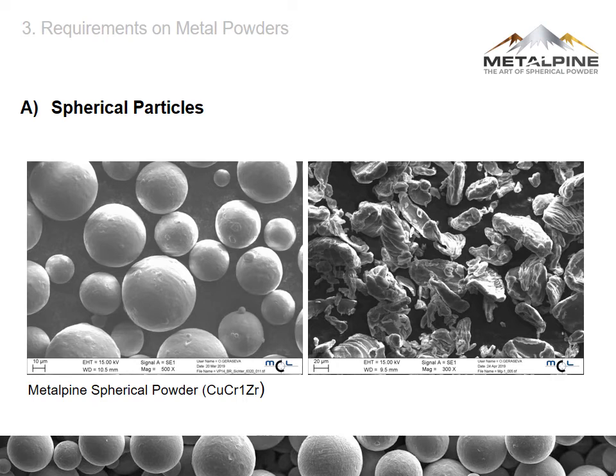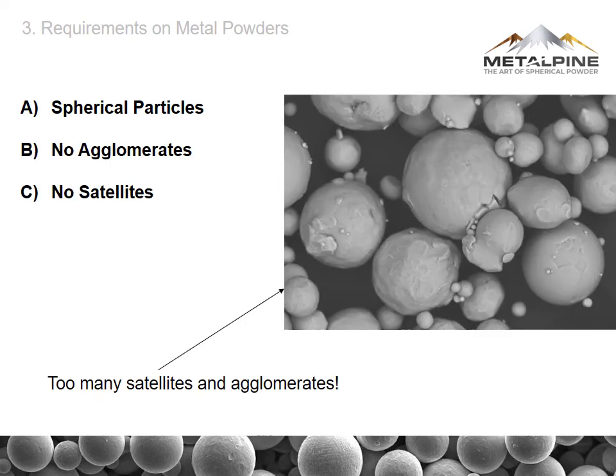So, of course, spherical particles are flowing better and have got a lower surface area than the particles which result from a grinding process here on the right. But you would also want to have only very few agglomerates, as any agglomerate may increase the probability of defects in the printed parts.